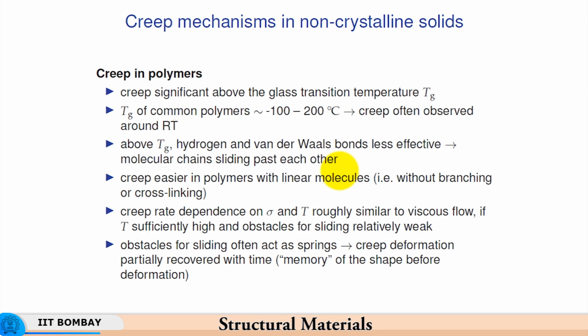So, if there are linear polymers without any branching, then you have much lesser resistance to creep. So, it all depends on whether you want it to creep or whether you want to build creep resistance into it. If you want to build strength into the polymer against creep, then you need to have branched polymers or cross-linked polymers which will have relatively stronger bonds with each other. Even if the van der Waals forces and hydrogen bonds become weaker, still you have so many of them that they can still pose a significant resistance to creep.